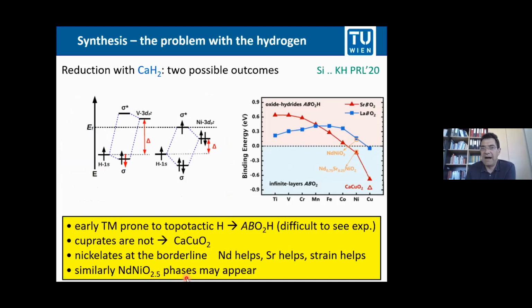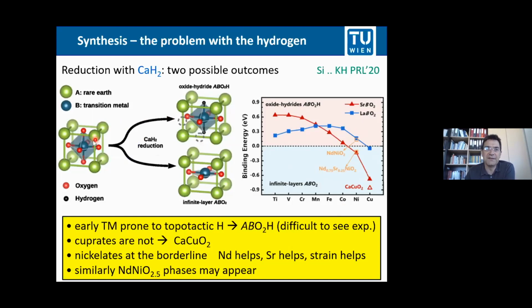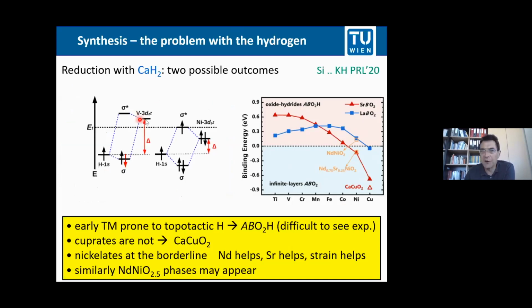Why do we bind the hydrogen? It's a simple DFT calculation and it's a simple understanding. If you have the early transition metal oxides, the vanadium, for example, or titanium, the z-squared orbital, that is the orbital that points in the direction of the hydrogen. It's unoccupied. And then if you put in a hydrogen atom, you form a bonding, anti-bonding pair. And therefore you gain energy.